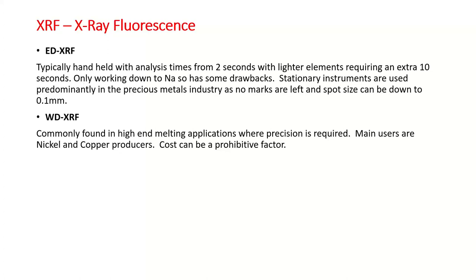So typically EDXRF, the energy dispersive, is what is in a small handheld system, and it can be in some benchtop systems. So it'll be used for around about 2 seconds for what we call the heavier elements, so from titanium upwards in the periodic table. 2 seconds on a handheld system is quick enough to give you a very good, reasonable result from your sample to be able to say what type of metal it is. If you need to go below there, so down to sodium on a handheld, so taking in aluminium and magnesium, silicon, these sort of light elements, then you have to increase the measurement times to about 10 seconds. So in all, you're looking at a 12-second measurement time. So very good.